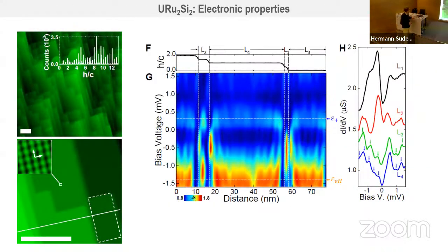We have been focusing on these surfaces where there are lots of terraces, and the terraces are relatively small. When you take a look at the conductance here on a color scale, when you go through different terraces, you see that the conductance changes a lot. So when you do scans like that and you plot the curves, you see a lot of small peaks here. And everything is blurred. The superconducting properties are kind of blurred inside these peaks. And it is quite difficult to understand, right?